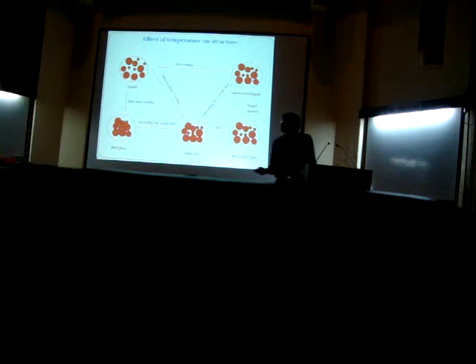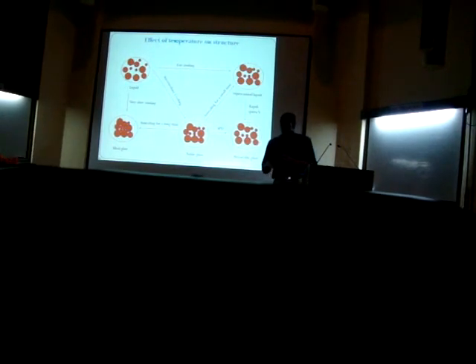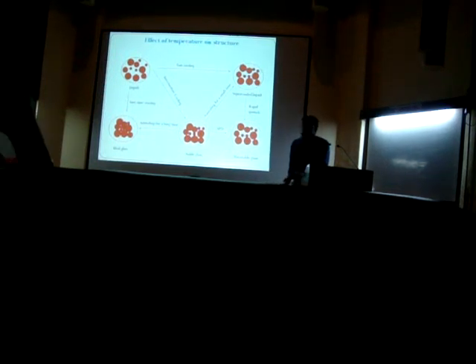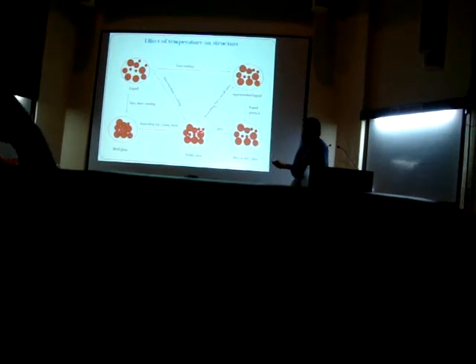It is not under too much strain. And this glass, if you anneal for a small amount of time, not close to the TG, it goes to the supercooled liquid state. The supercooled liquid state would have some extra spaces between atoms. And if you cool it for a long time, this can either go to an ideal glass or it can become a crystalline structure. The ideal glass is generally extremely brittle, and a supercooled liquid structure is mostly open. The implications of this will obviously come later. But this is the most important diagram. Severe plastic deformation can also result in a metastable glass. So I'll go ahead with what we have done.